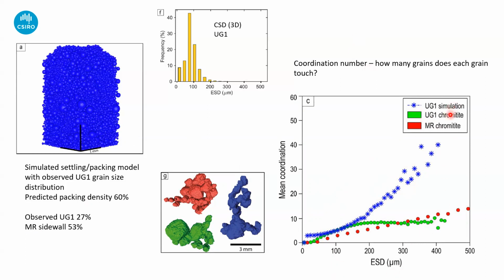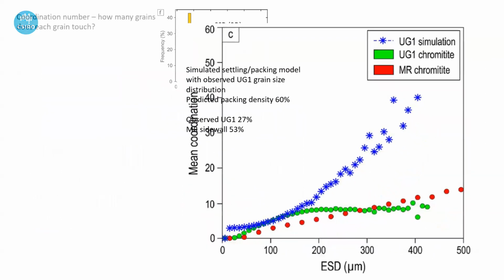If we look at the UG1 sample and the Merensky Reef sidewall sample, we find that they both fall well below this distribution. Down at the bottom here, a typical coordination number is around 4 or 5 for the average size grain. But if you look at the bigger ones, the observed distribution starts to diverge considerably from the theoretical one. The Merensky Reef chromite is still linear. The UG1 chromite distribution tends to flatten out. But the point is they're both distinctly different from the theoretical loose pack one, and they're quite similar to one another. So again, this is just one study, but I think this has got some real potential as a way of putting some different kinds of textural parameters on cumulate rocks.